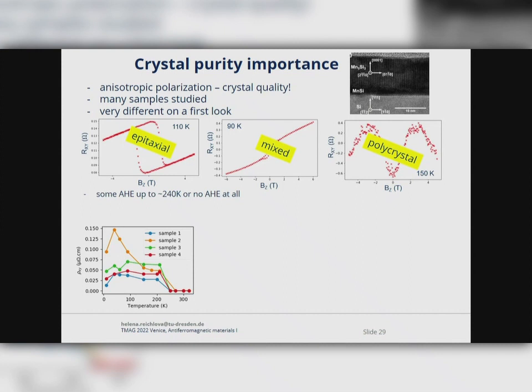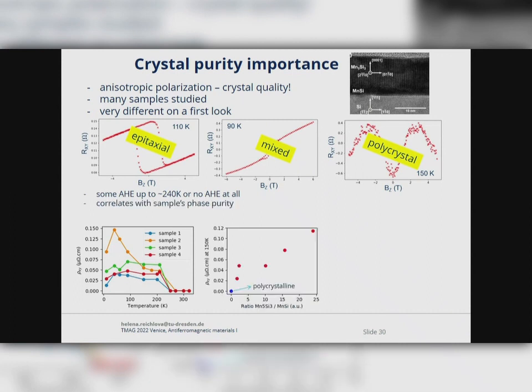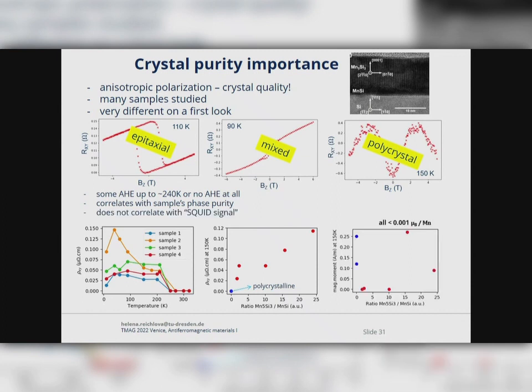Although they share some features, like the absence of the signal above the Néel temperature, the magnitude of the anomalous Hall conductivity is scattered. When we plot the X-ray analysis, we extracted the ratio of the Mn5Si3 and the manganese silicon spurious phase. Here I also artificially add one polycrystalline reference sample which we prepared. You see that the anomalous Hall resistivity correlates, increasing with the increasing ratio of Mn5Si3. This is in contrast with the SQUID measurement, where the moment we measure cannot be correlated with our ratio of Mn5Si3, and also cannot be correlated with our anomalous Hall conductivity.